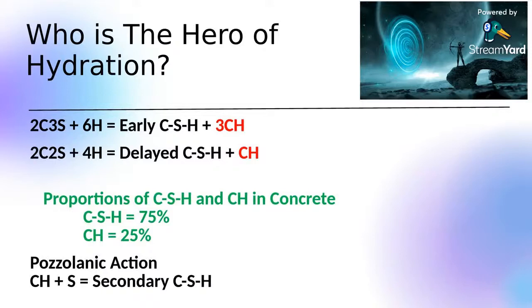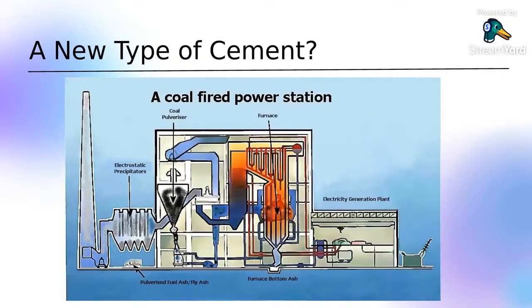pozzolanic action. So what is pozzolanic action? Pozzolanic action is this reactive silica which you find in fly ash. And jokingly I say, when you compare your cement manufacturing process, how is your cement manufacturing process? In cement manufacturing, you bring limestone, you bring siliceous clay, you burn them, you get clinker, you grind the clinker, you get cement. So cement manufacturing is a simple two-step process: burning, grinding, and you get cement. Now, what is the temperature in your kiln when you are burning the raw material? Surprise, the same 1200 degrees which is inside the furnace in your thermal power station. And because that 1200 degrees temperature creates cement, this 1200 degrees temperature in your power station creates reactive silica and alumina.